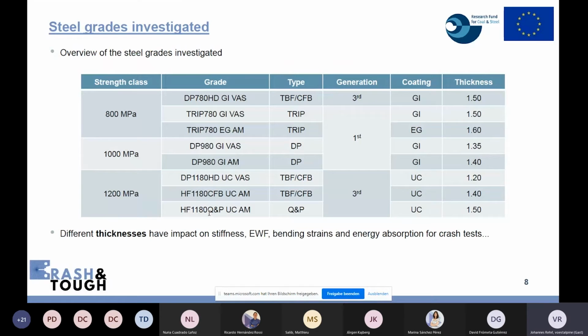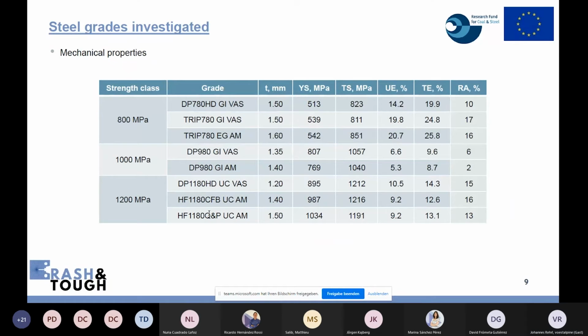The grades had different thicknesses, so please keep in mind that different thicknesses may have an impact on stiffness, on essential work of fracture, on bending strains, and energy absorption for crash tests. This table shows you the mechanical properties of the steel grades investigated.